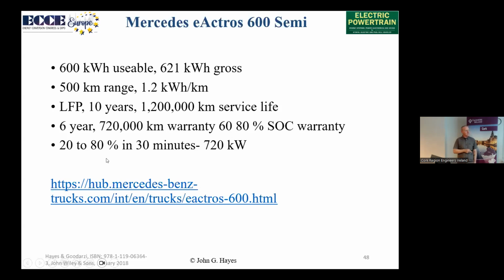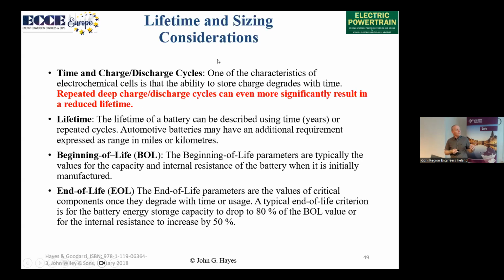And they will say they'll do a recharge from 20 to 80% in about 30 minutes. 60% of the pack is 360 kilowatt hours, so to do that in half an hour is 720 kilowatts. So we need our battery to last, and we need it to be able to handle charge-discharge cycles.